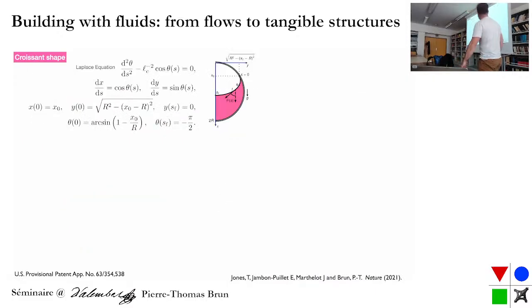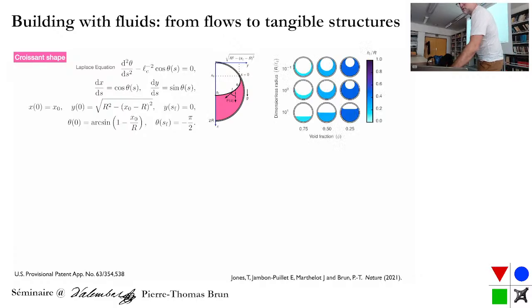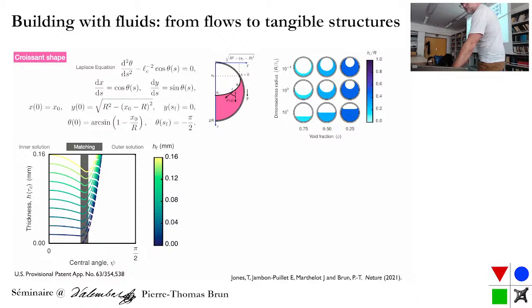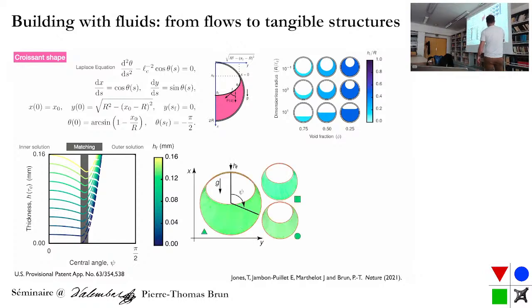Okay, the bottom part, it's again the same equation as the pendant drop, but just in a bit of a weird geometry. You can find all kinds of shapes, but it so happens that we have a void fraction of 50% as we predicted before, and our dimensionless number between the radius and the capillary length in this case is more or less 1. So we tend to get these shapes. So that's the bottom. We have the top. You can match both, and if you match both, you get essentially this shape. So the green is the experiment, the red is the theory, so it works fairly well.